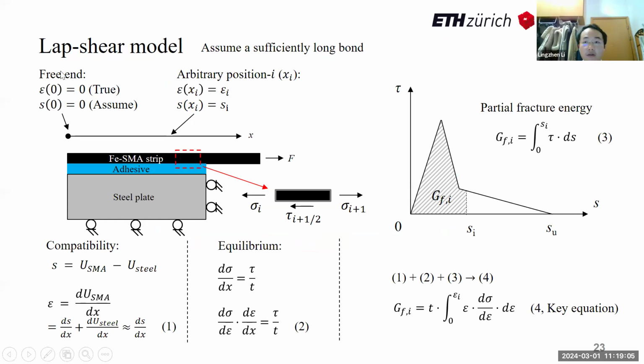Prior to my PhD work, there was already a lot of research investigating the bond line and also the lap shear behavior, especially in the field of CFRP bonded and unbonded strengthening. But there is a major difference between my case and the previous cases. CFRP is typically known as a linear elastic material, but our shape memory alloy features a nonlinear stress-strain behavior, which brought some difficulties for applying the CFRP bond models to my case. Therefore, I built my own lap shear model.